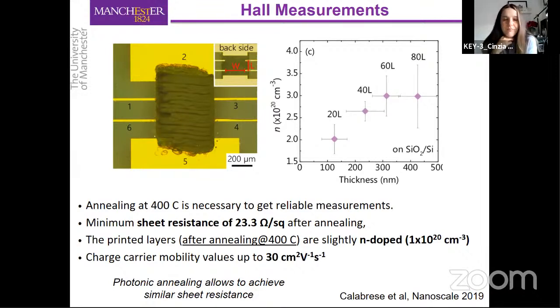So the idea was basically to get some indication on the doping of the film. Is this graphene film doped, and how much is the doping, and so on. And in order to perform Hall measurements, we had to anneal at 400 degrees C.